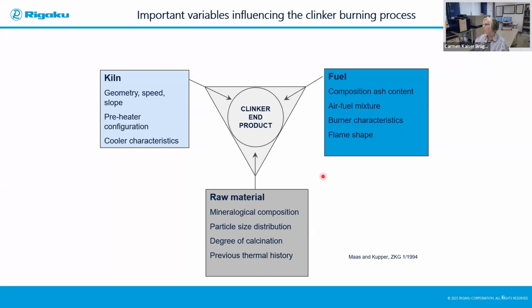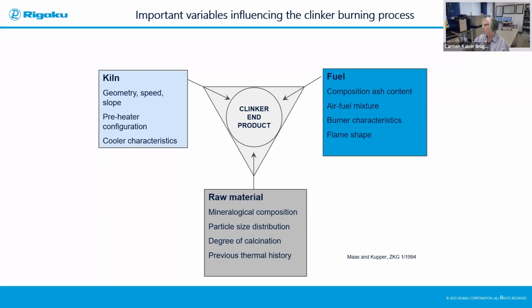So if we look now at the fuel, when we use the fuel in our kiln, as you saw in the process, we will have an ash, and this composition of the ash will add to the clinker. So it's a clinker ash pickup. This will influence the composition, and it will influence these phases that we have. The burning characteristics and the flame shape will also be influenced. And basically the air and fuel mixture will also be influenced.